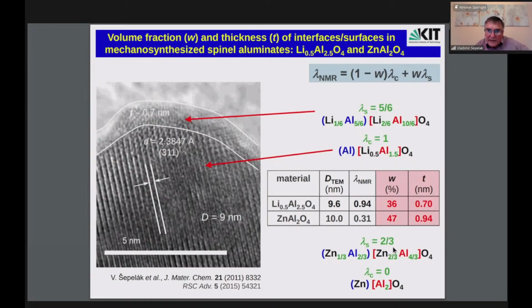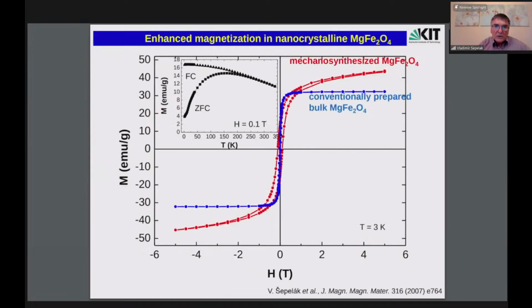And then we see that the volume fraction of the interfacial region is huge in mechanosynthesized material, exceeding sometimes even 50%. And the thickness, if we know the size of nanoparticles, we can calculate, which is about 1 nanometer, typical for mechanosynthesized complex oxides. The second example, which I would like to show you, is a separation of surface effects from